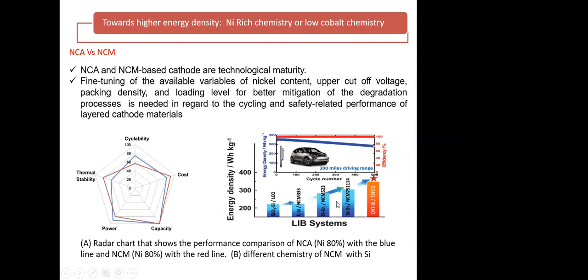Once you are increasing the nickel content, the thermal safety concerns are increasing. Because nickel plus 2 gets converted into plus 4, this gives a lot of heat. So that's why nickel 811 chemistry is not stable and it's getting blasted. So now 532 and 622 along with silicon are delivering nearly 300 watt hour per kg, and for getting 500-kilometer range, this NMC with silicon graphene is the right choice, and most of the industries are working on this chemistry to achieve 300 plus energy density.